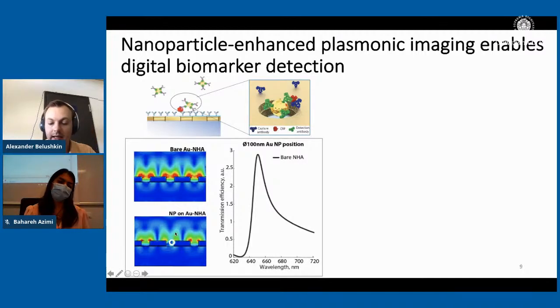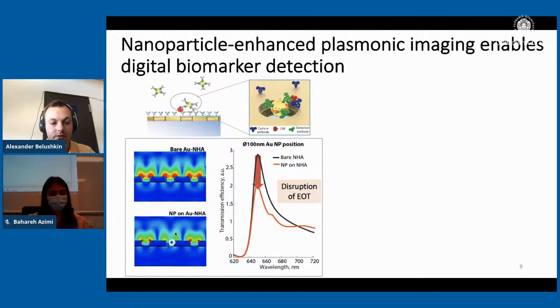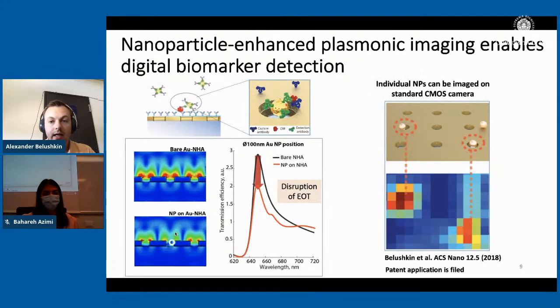Whenever we have the antigen in the solution, the nanoparticle can bind on the nanohole array surface. And when the binding happens, the gold nanoparticle locally disrupts the extraordinary optical transmission. This results in far field suppression of the transmission, so basically we can see those individual small dark spots. In this way, we can detect individual nanoparticles on the gold nanohole array surface. I should highlight that although both the nanoparticle and the nanohole are sub-wavelength in size, the nanoholes about 200 nanometers and the particles around 100 nanometers, we can still resolve them in a conventional diffraction limited setup, basically a small microscope, because of those plasmonic enhancements.